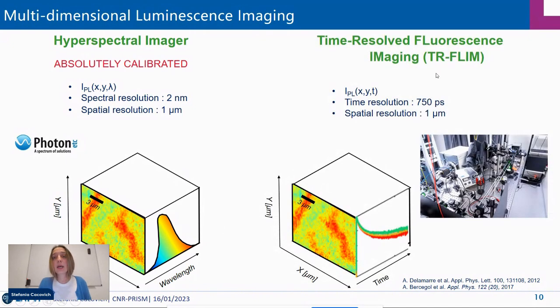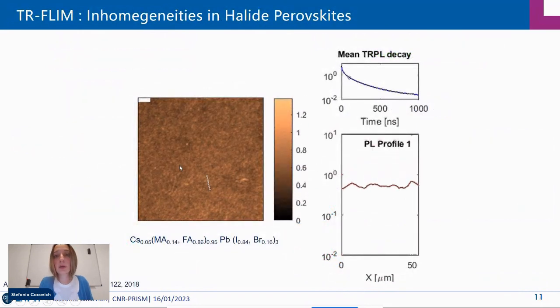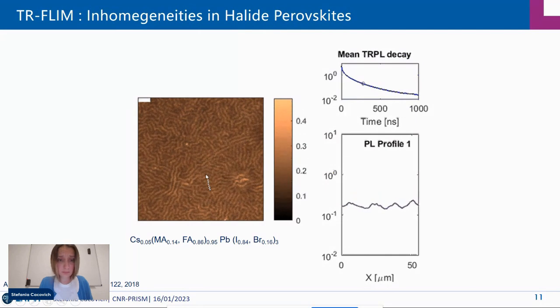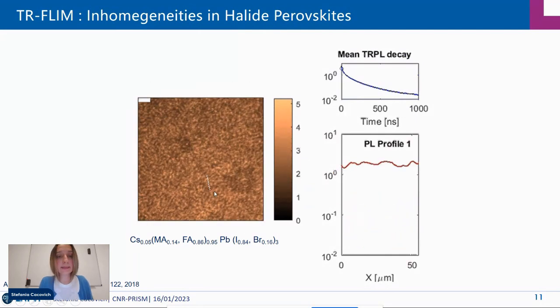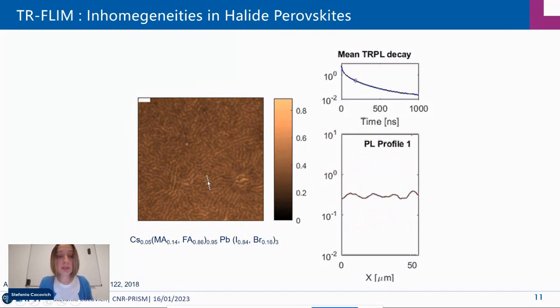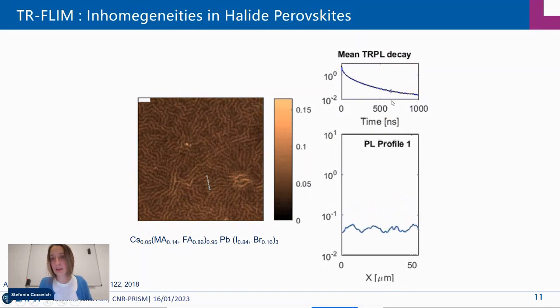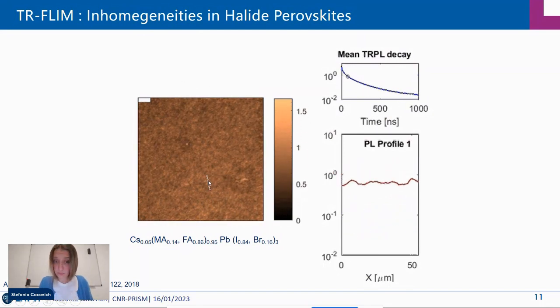We have then another setup that is time resolved. So it's a time-resolved fluorescence imaging (TR-FLIM) setup. In this case, the datasets are still cubes, so they are three-dimensional, but the third dimension is time. And so this allows us to acquire maps, and to each pixel of this dataset, we can associate a time-resolved decay. So this is an example of a TR-FLIM acquisition. Here you see a triple cation double halide sample, a thin film just deposited on glass. Here we are following the time-resolved decay, and here we have the local PL profile.